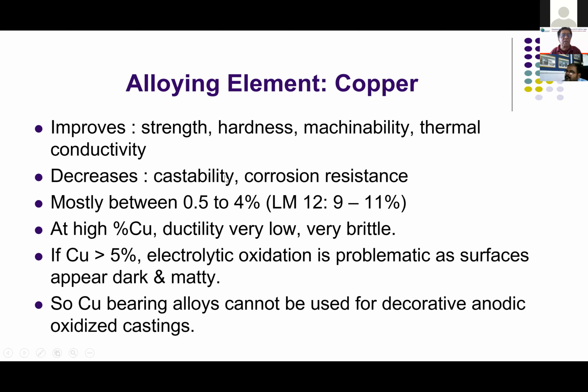Here, if you come, what are the properties of copper? It improves the strength, hardness, machinability, and thermal conductivity. You are all familiar. Copper is a very good conductor of thermal as well as electricity. When you add copper to aluminum, it improves the thermal conductivity of the alloy. It decreases the castability. Unlike silicon, it reduces the fluidity, and also copper gives rise to problems in corrosion resistance.